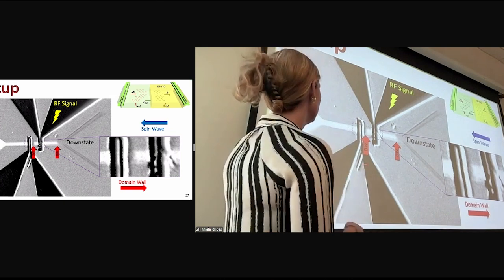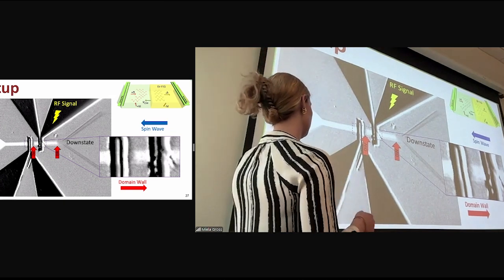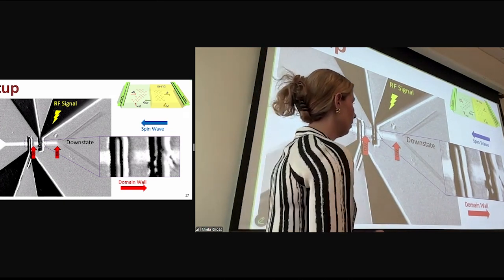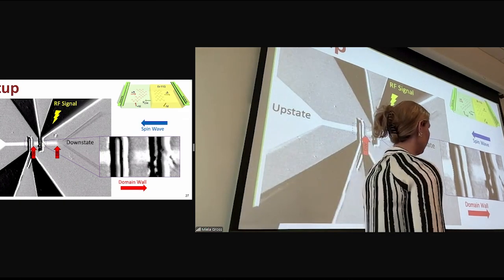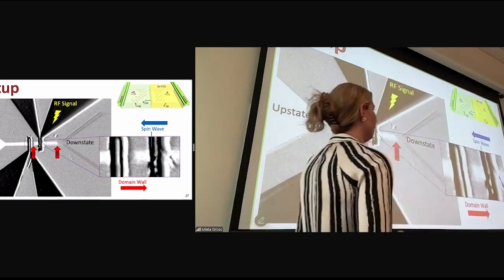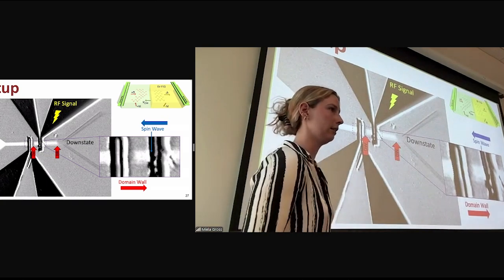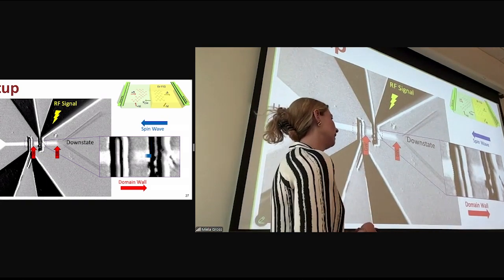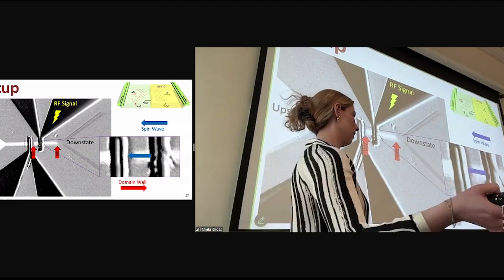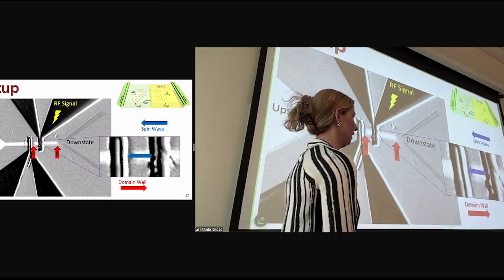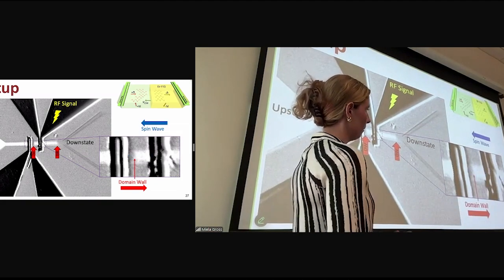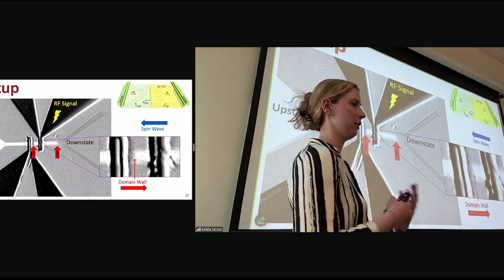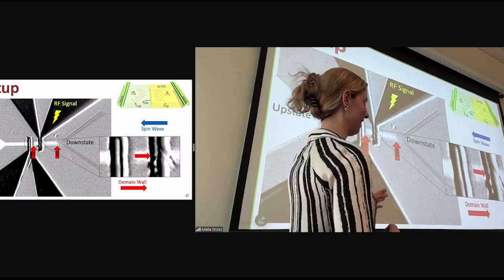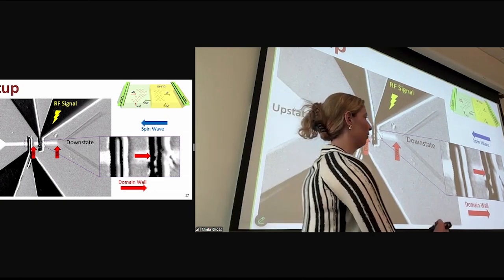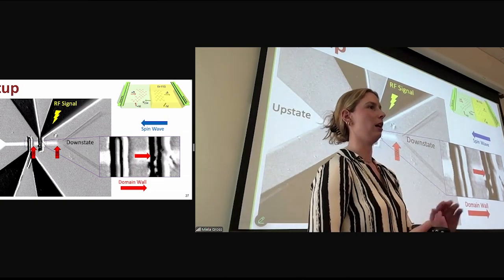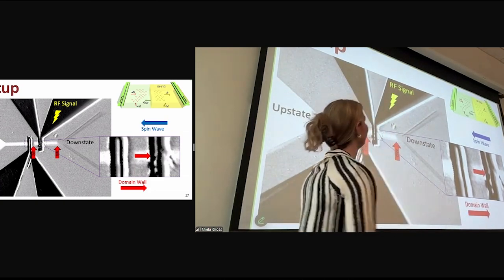So for our experiments, we're looking at stuff around the antennas, which is why I blew this up over here on the right. So what we do is we send in an RF signal through one of our antennas here. It excites spin waves radiating away from the injector antenna until it reaches a domain wall here. Once it reaches the domain wall, that exchange in energy will propagate the domain wall to the right towards the injector source. So it's going to move in the opposite direction of the spin waves.